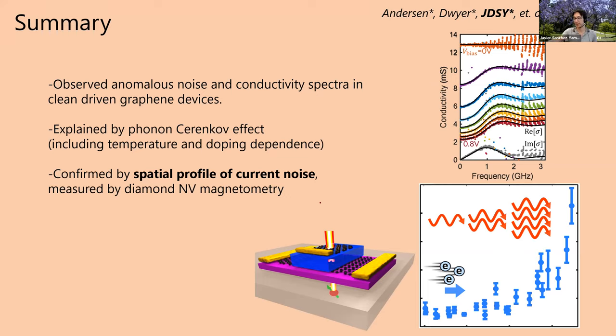Yeah. So I realized I went way too quick. I think I was too ambitious to include both the NMR and the noise. Normally I spend more time on the noise. What we know for sure, or what we're very confident about, is that the phonon population is growing exponentially across the sample. And then the question is, how does that affect the current noise? Our thinking is that the more phonons you have, the more scattering of electrons you get, and that will be some sort of Poissonian process. That will lead to increased current fluctuations. So the more phonons you have in some region of your sample, the more fluctuations you'll get in the current because it scatters with the electrons. Does that make sense? Okay.